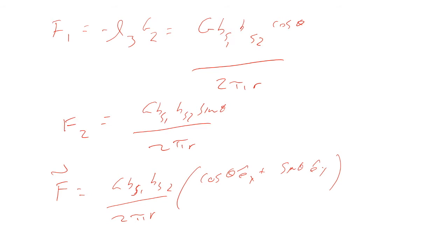What we see right away is that if these are parallel, we're going to have a positive force and they're going to repel. And if they're of opposite sign, then they're going to attract. Which makes sense. But this is just working through it. All the problems you can set up follow the exact same process.